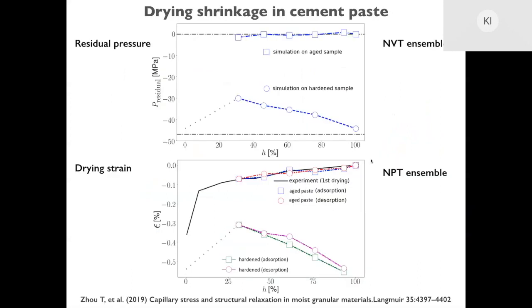So the next thing that we could do was to study the drying shrinkage in cement paste. So here, as I told you, is the part where we put back the capillary forces in the solid and we relax the structure with molecular dynamics. So we did this in two different ensembles. In the one ensemble, NVT, we keep the volume constant and we measure the pressure. And in the other ensemble, the NPT, we keep the pressure constant and we measure the shrinkage, the volume differences.